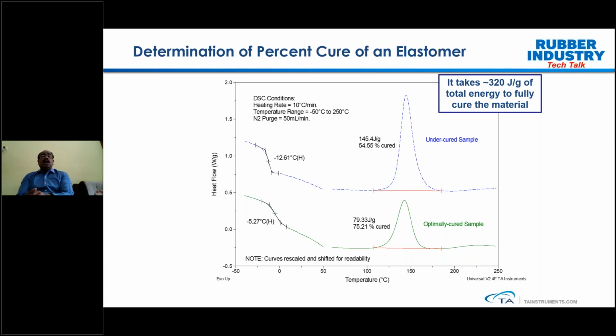Whereas the blue compound shows a lower Tg as well as a higher residual cure. This is the second time we are keeping the sample on the DSC, where we are seeing this thermogram behavior. So coming back to the blue curve, when you account the energy, which is higher at 145.4, if you take the ratio, the blue compound is cured only 55%. That is the reason we say that the sample is undercured, and that also reflects in your glass transition, which is at a lower temperature. So this way you can see how DSC is really helpful to understand things.